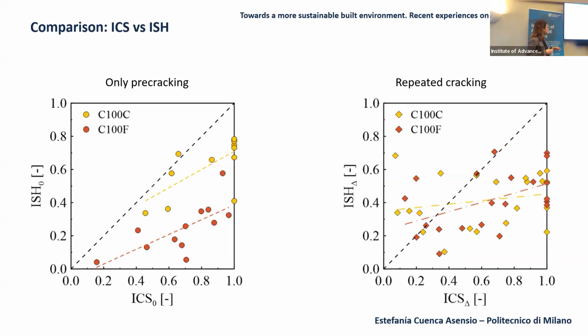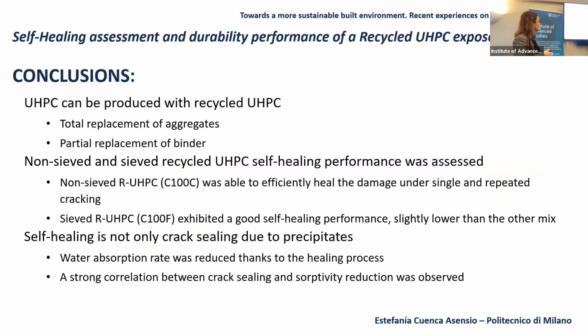Here we have represented the index of sealing and the index of healing, relating both values that I explained here. As you can see here, this is a little bit higher, and this is lower. But what happened with repeated healing? These are points randomly distributed, so there is not a clear tendency, but in this case the healing rate is constant, so it's not so good when we repeat or over a long time.